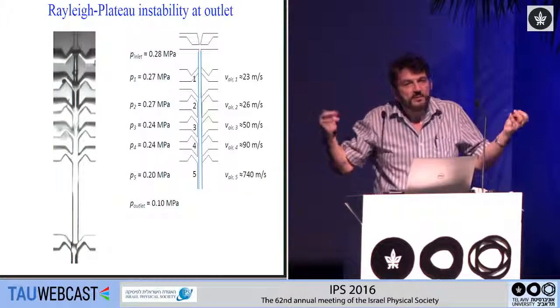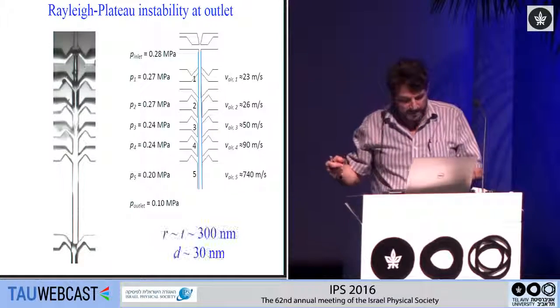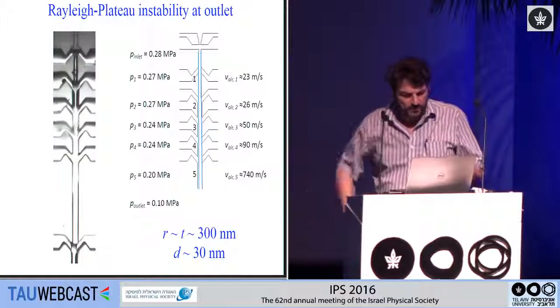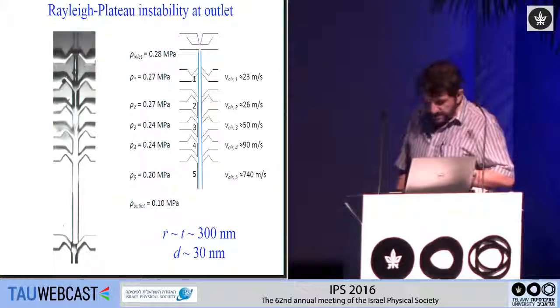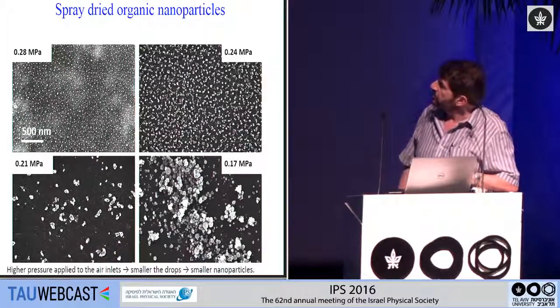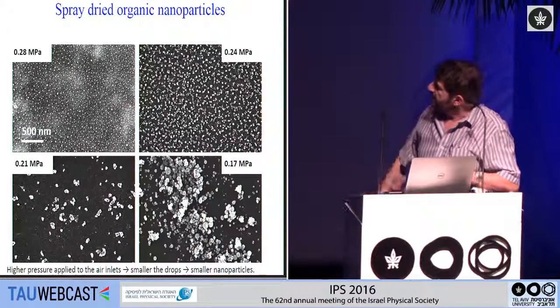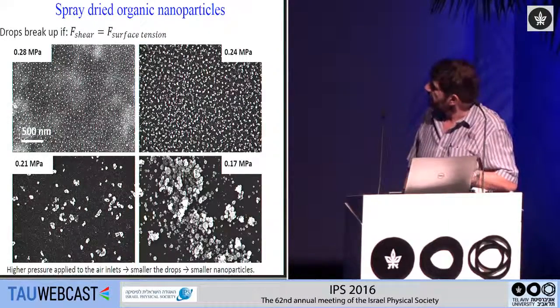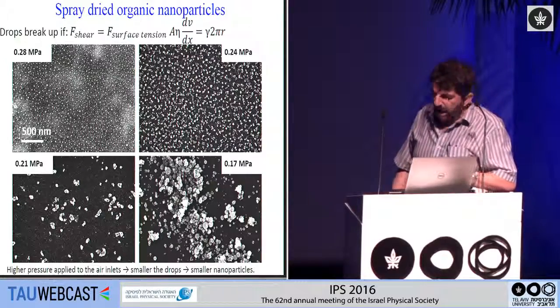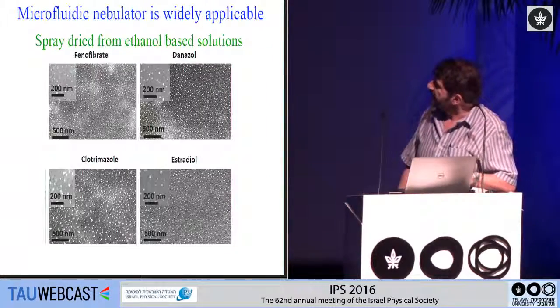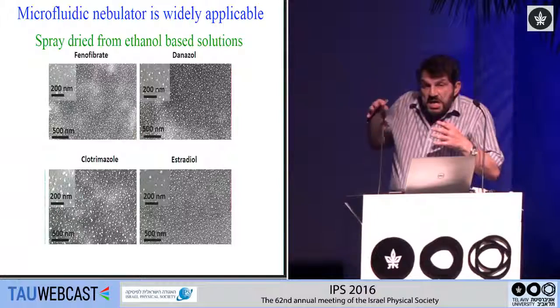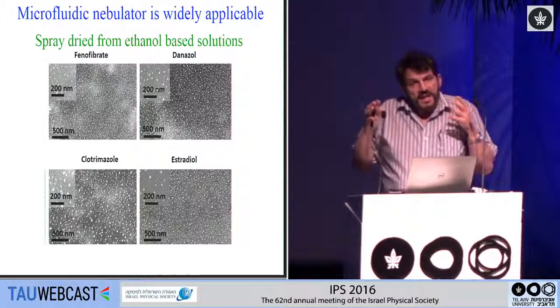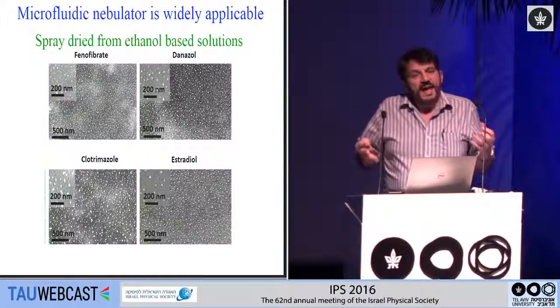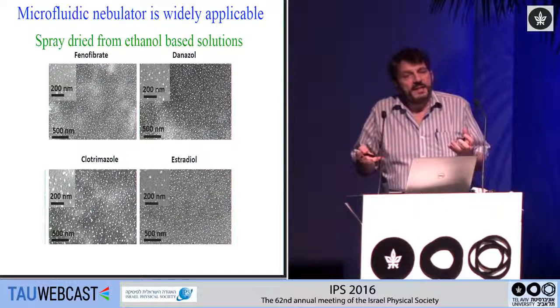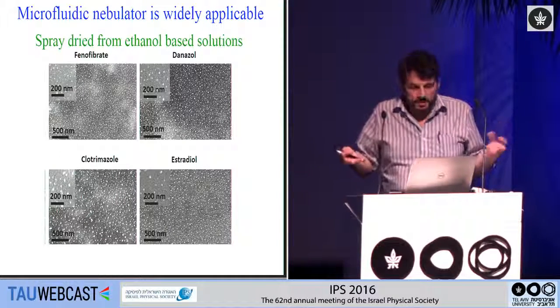The thickness of the ring tells you the size of the drops. And again, you can go through the same behavior. You see exactly the same type of behavior. You form nanoparticles. Their size depends on the velocity of the air. I won't go through the details. It works exactly the same way. And again, here's another way you can make, with all different materials, anything that you put in that precipitates from the solvent, you create these nanoparticles.